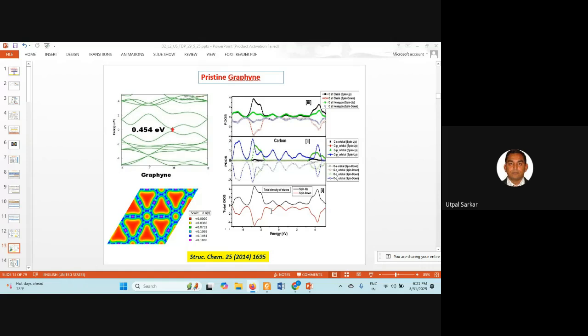So this is the basic band structure of pristine graphyne. Here you are seeing the band gap of 0.45 electron volt, and that is situated at the M point. It's a direct band gap semiconductor. And these are the participating carbon atoms. There are several carbon atoms, one in the benzene ring, another in the acetylene linkage. So which carbon atoms are basically contributing near the edges of the Fermi level, that you can characterize. You see here that both the carbon atoms, hexagon as well as chain site, are contributing near the Fermi level.